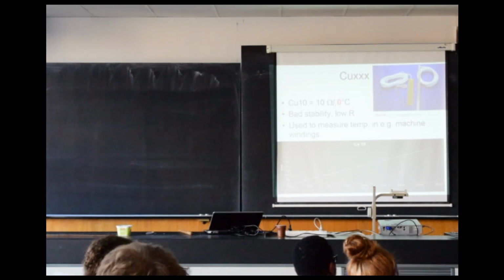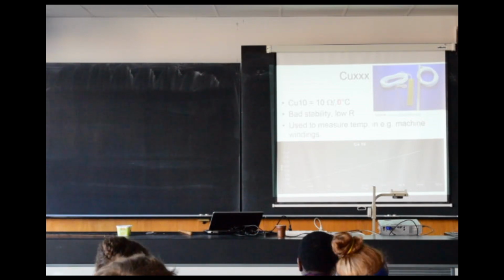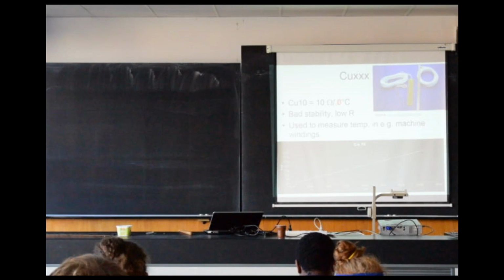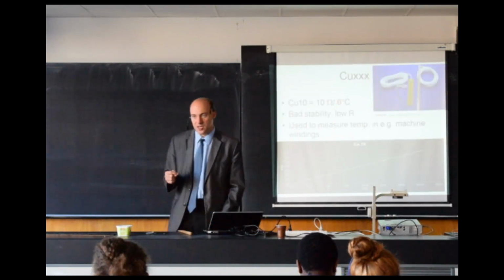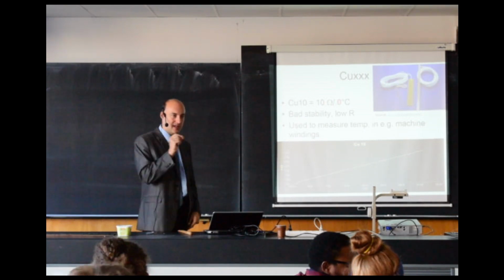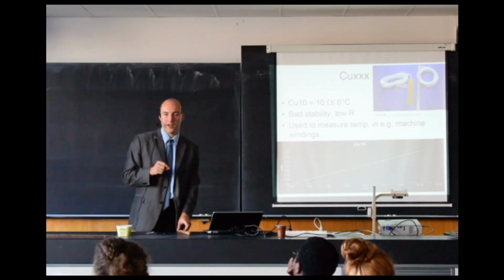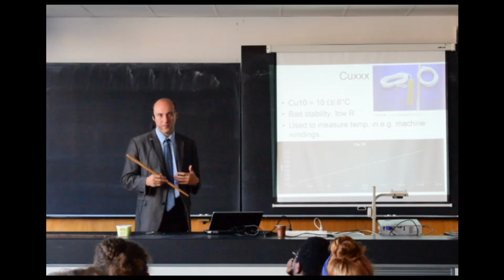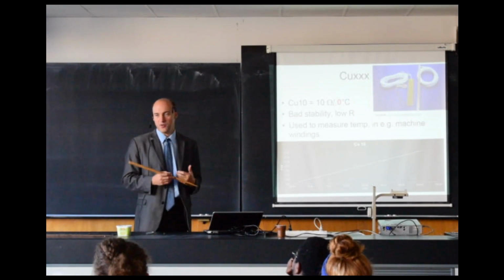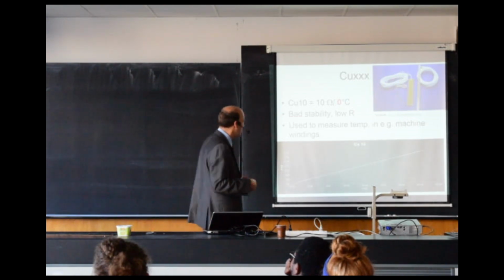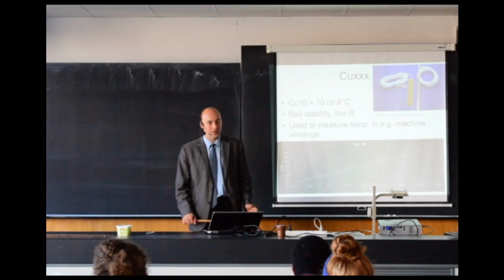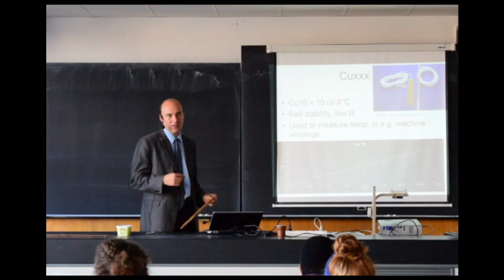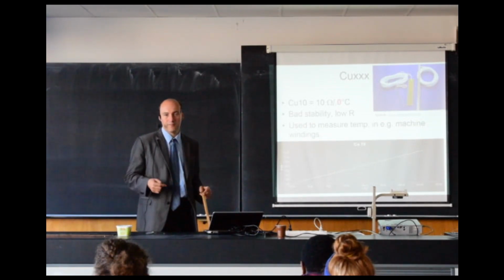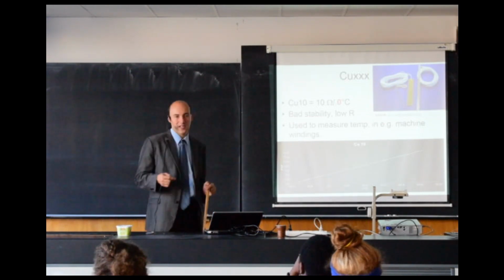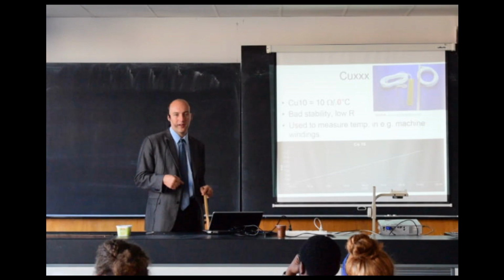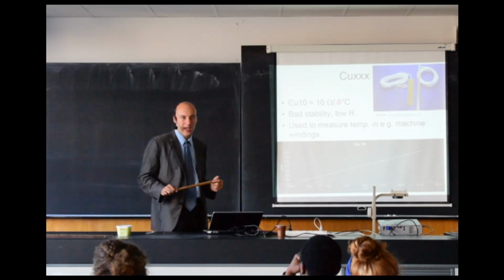So the typical application of this kind of sensor is to measure, for example, winding temperature in electric machines. Since the sensor is very thin, you can insert it quite easily right into the winding of an electric motor, read the temperature during an experiment, and then you can remove the sensor. In this kind of application you don't really care about long-term stability. You just want to know, okay, now I have 90 centigrades or 50 centigrades, and if the sensor will not be reading the same temperature in 1 year, then that's not an issue.